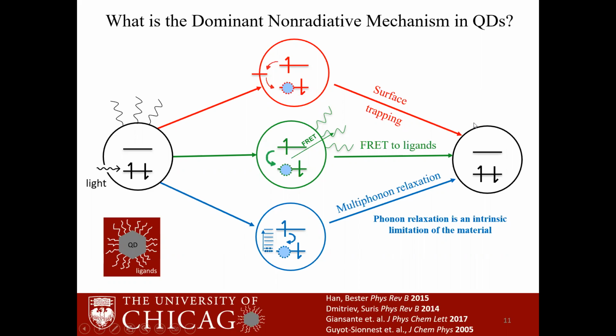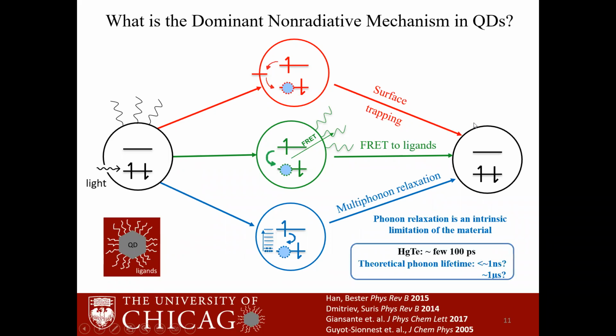What is the rate for multiphonon relaxation in quantum dots, and how does this compare to the relaxation rates that we currently see in our detector materials? Mercury telluride quantum dots have relaxation rates of the order of a few hundred picoseconds. There have been theoretical calculations, semi-classical calculations, which predict that the phonon relaxation rate should be quite fast, faster than around a nanosecond.